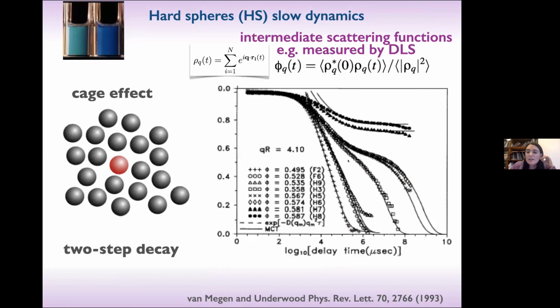So this so-called two-step decay is the typical feature that happens close to a glass transition. In hard spheres in particular, it is easily understandable in physical terms by means of the so-called cage effect, in which, when you pack the hard spheres more and more, a given particle will feel more and more the influence of its nearest neighbors. So there will be a short-time relaxation when this red particle is able to explore its cage, the cage of the configuration in which you started the measurements.